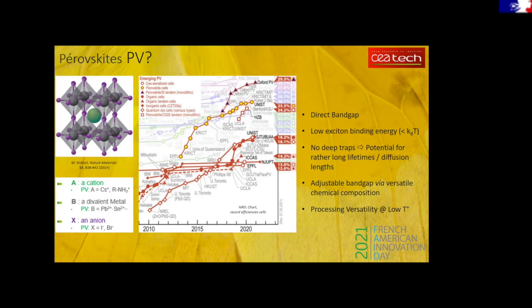And the solar cells can be coupled with, for example, silicon technologies, not only. And the record with these tandem solar cells is close to 30%. This class of materials is very interesting because of fundamental properties like a direct band gap, a low exciton binding energy, important diffusion length of carriers, and an adjustable band gap. By modifying the chemistry of the crystal, you can adjust the band gap or the color.